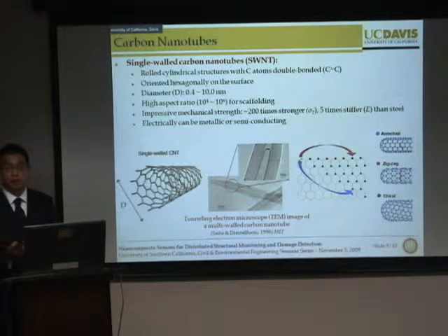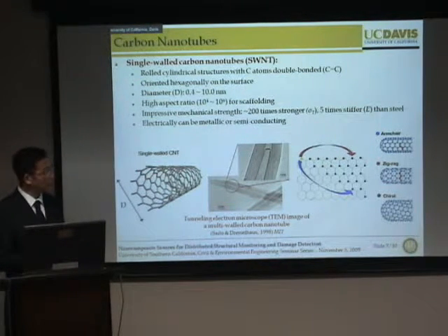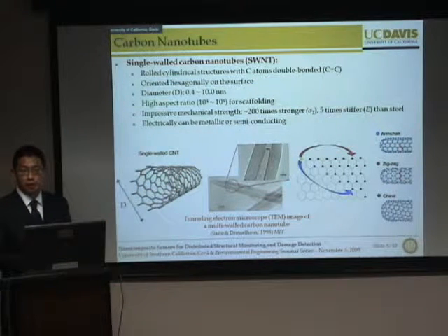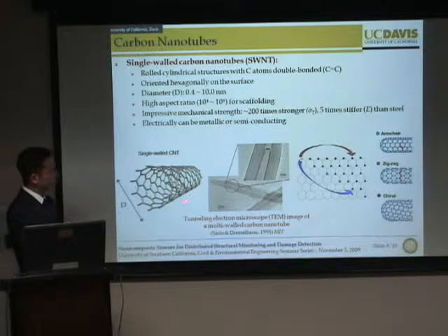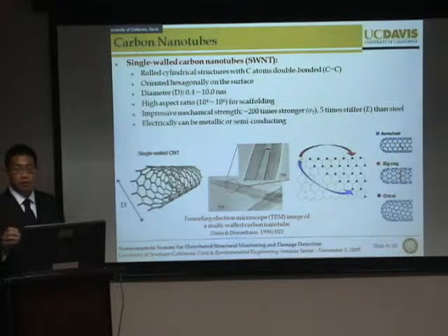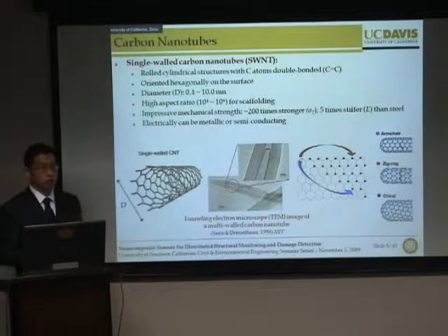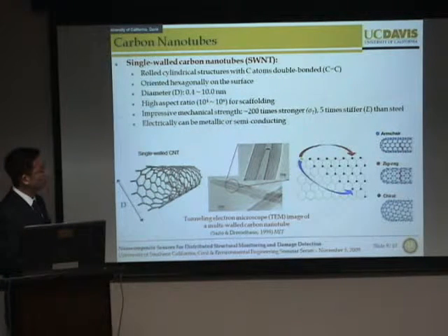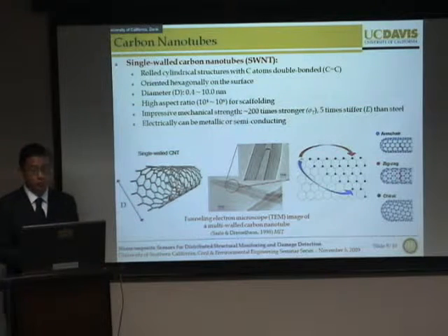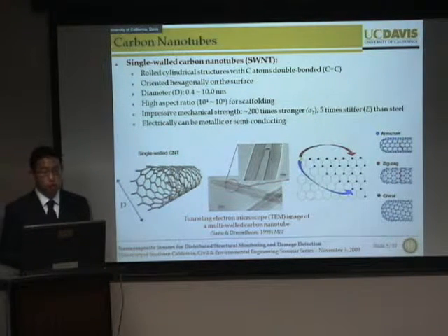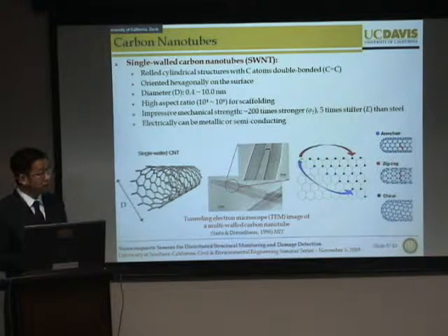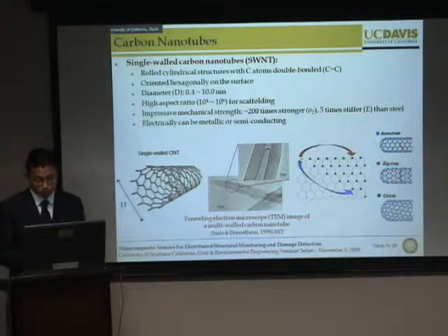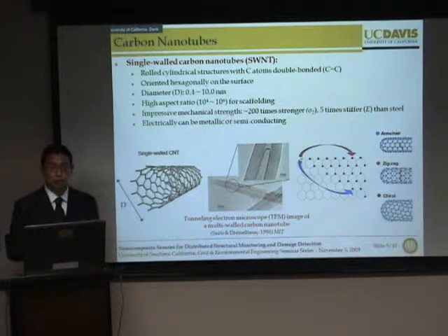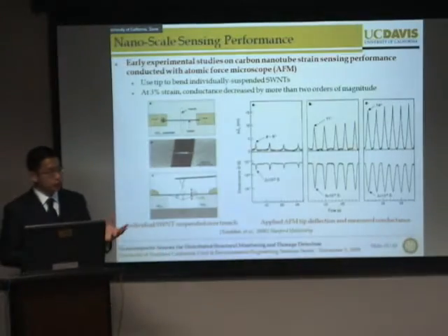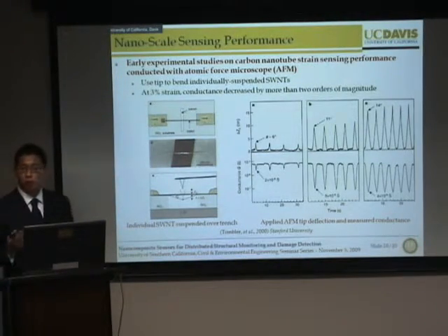And also associated with that high aspect ratio is an incredibly large surface area. Now, this surface area is extremely advantageous for us because we can actually modify the intrinsic material properties of an individual carbon nanotube by molecularly attaching different species onto its surfaces, also known as functionalization. But when we look at just a pristine carbon nanotube in itself, it already exhibits impressive material properties. For example, its mechanical strength is 200 times stronger and 5 times stiffer than steel. And electrically, it can be metallic or even semiconducting, depending on how you roll your graphite sheet to determine your carbon nanotube structure.